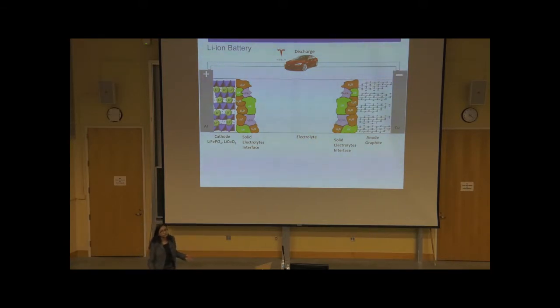Now, two things to note here. When we are charging the batteries and these lithium ions are traveling back, they react with the degradation product in the electrolyte, and they form a solid electrolyte interface on the graphite surface. It is actually a layer of decomposed product, but in the case of lithium-ion batteries, it worked out pretty well because it prevents further degradation of the graphite anode, but at the same time, it does not block these lithium ions from moving in and out. So that's great for lithium-ion batteries.